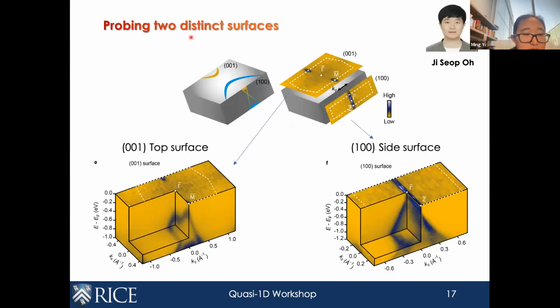To demonstrate this experimentally, work carried out by Ji Seop Oh, he measured independently the top 001 surface and the side 100 surface. And again, you see very distinguishable Fermi surface topology. So here on the top surface, we have the bright spots. On the side surface, we have the quasi-1D features. This is consistent with the beta phase of the bismuth iodide.